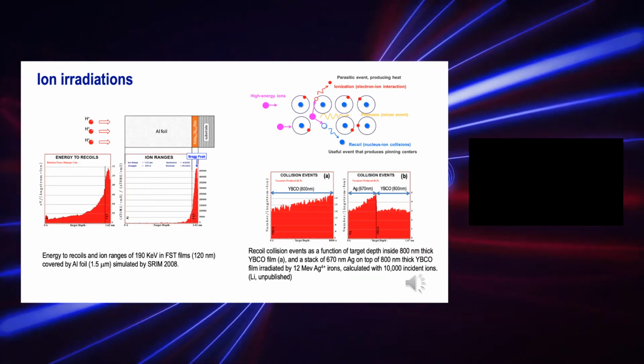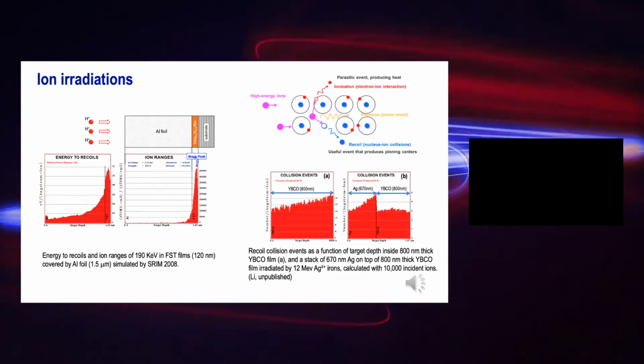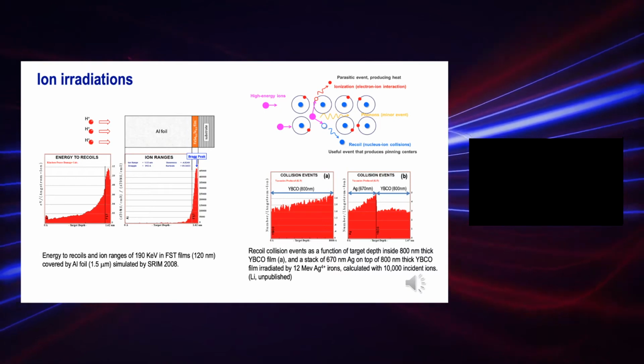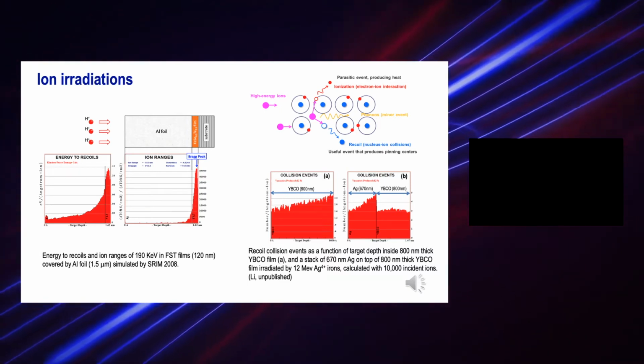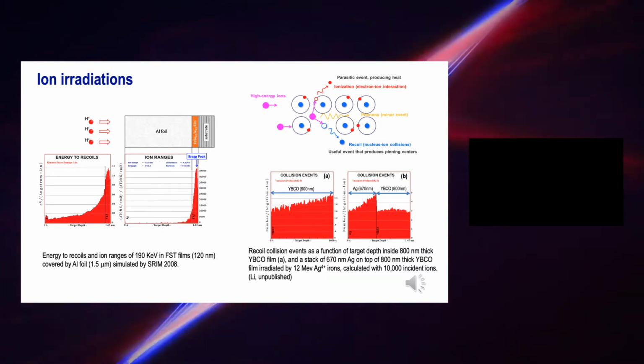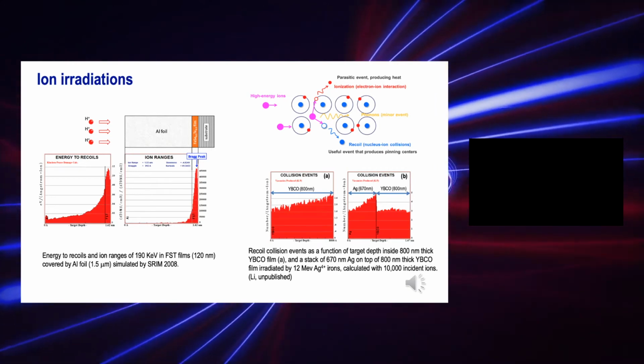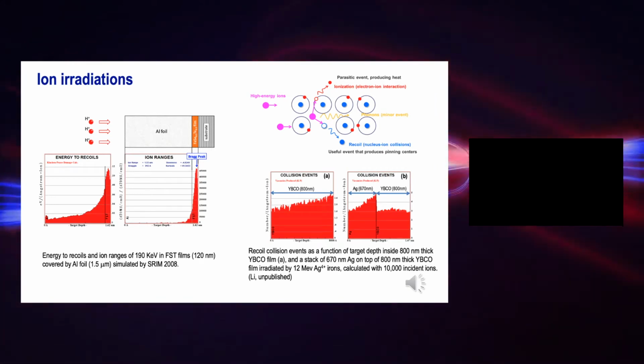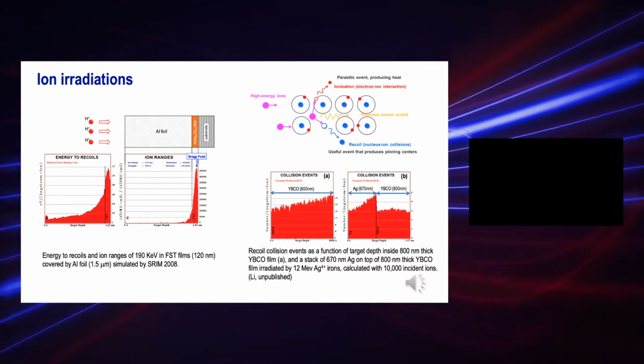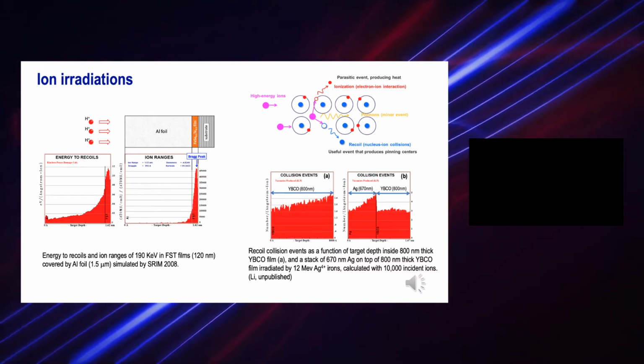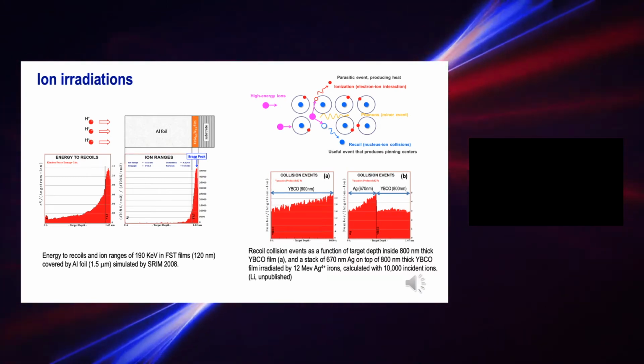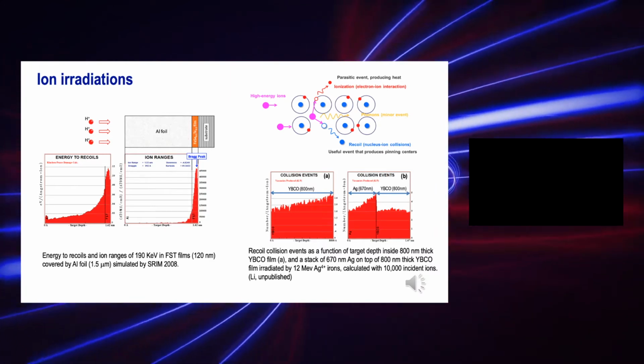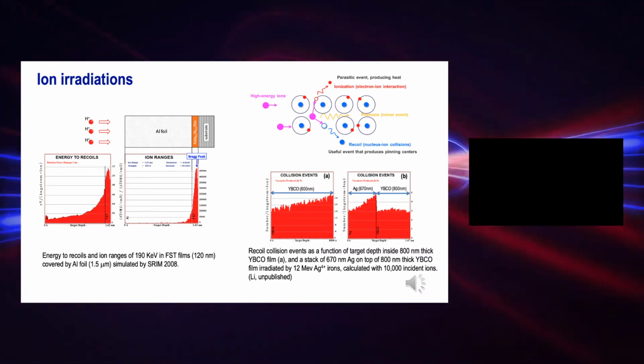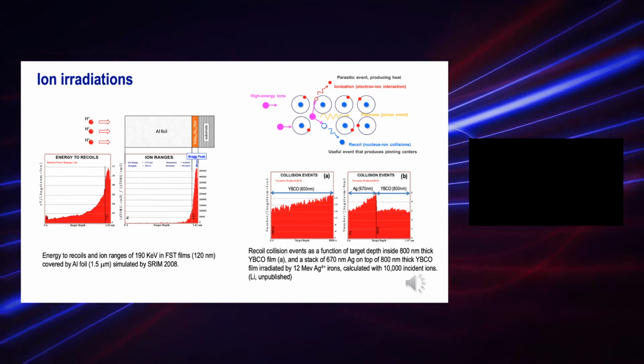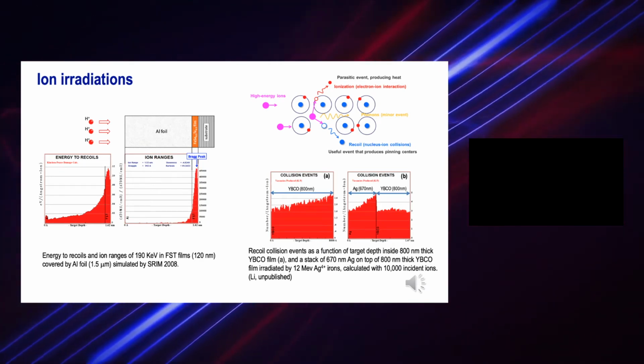In this case, we use ion irradiations. Now when we're sending in the high energy ions, you can have several events happen in the materials. You can have these parasitic events that produce heat, such as ionizations, or just simply rattle the lattice and produce phonons. Those are the minor events. What we want is a recoil event. This is the collision between nuclei and ions. And this is the event that will be useful to produce the pinning centers here.